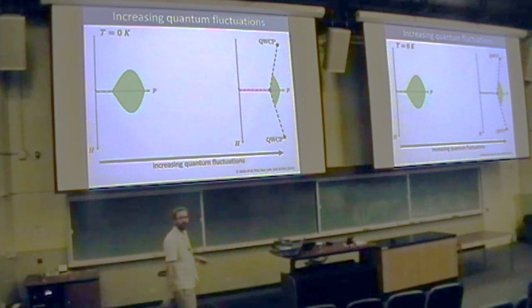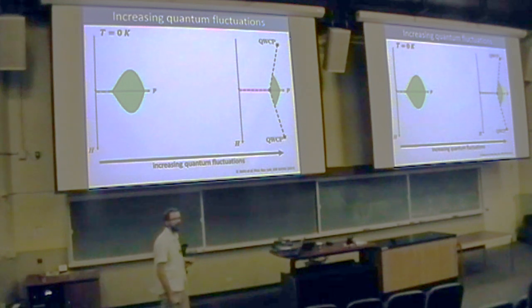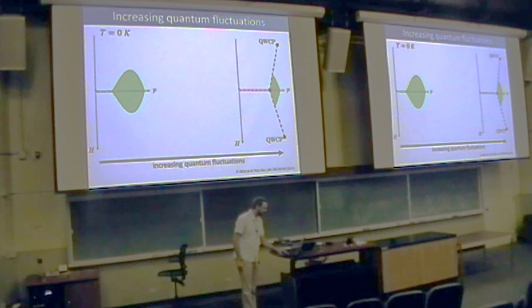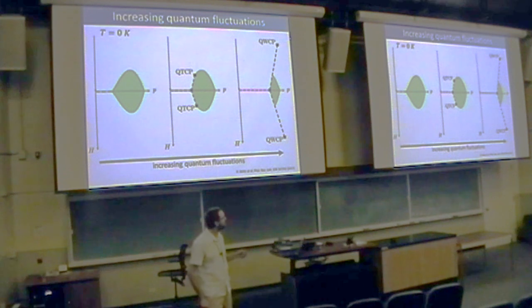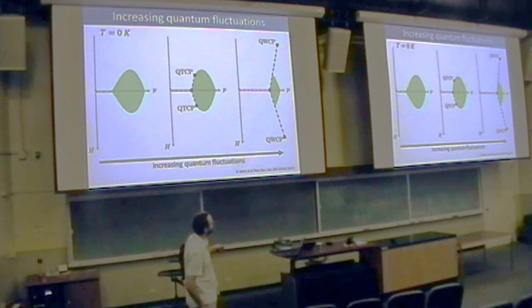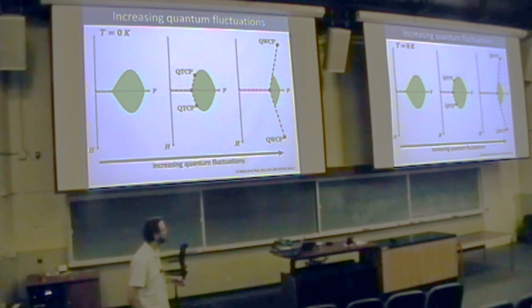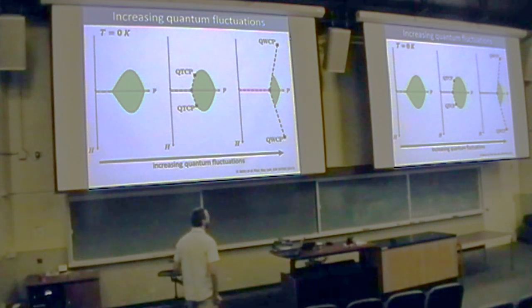And so if we believe this, that means that lanthanum chromium germanium 3 is an example where we have the large quantum fluctuations. Now they also found an intermediate case, where you have the first order transition line that terminates within the dome of new magnetic phase. And so in this case you have a first order line that changes to a second order line at T equals 0, and so we call this a quantum tricritical point.